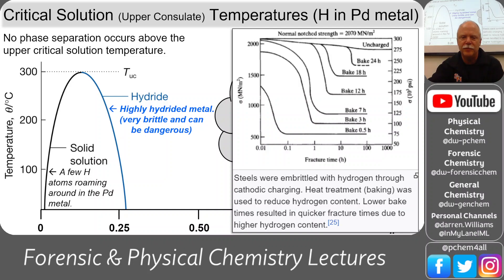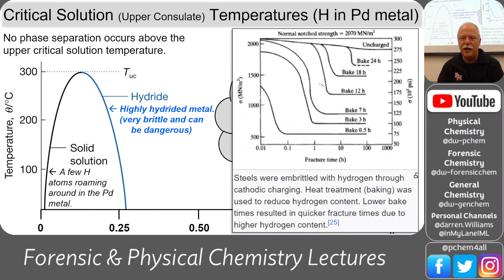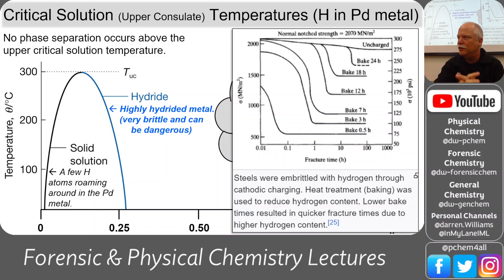If you have a metal pipe with something that has a lot of hydrogen in it, that hydrogen can cause the metal pipe to become brittle, meaning it won't hold the pressure you expect. This is yet another reason why going to a hydrogen economy could be problematic - pumping hydrogen around in metal pipes can cause hydrides to form, which is dangerous. Here's an example of a steel pipe embrittled with hydrogen. It was fracturing in between a hundredth and a tenth of an hour. This shows how they treat it by baking the hydrogen out - baking for 30 minutes, three hours, seven hours, twelve hours, and 24 hours - getting above ten hours of fracture time. This shows the dramatic change in tensile strength when you put hydrogen in steel and other metals.